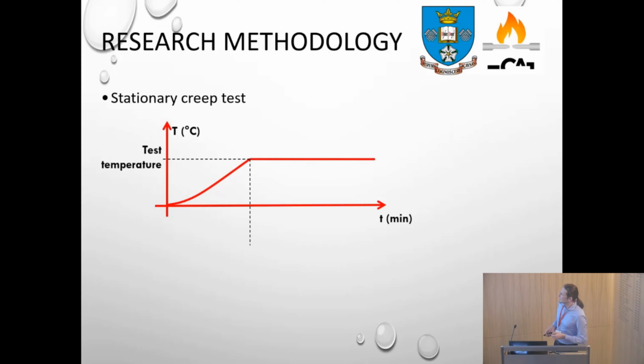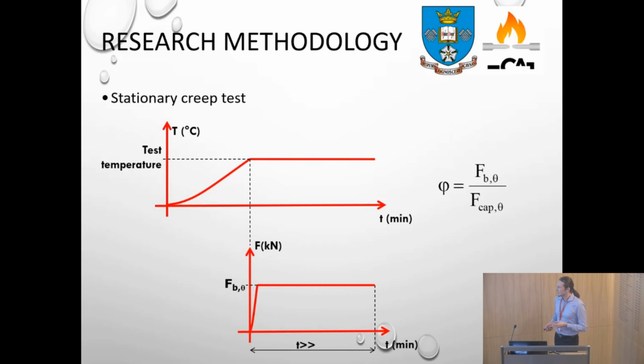Afterwards, we did the stationary creep tests by applying an axial force value, which represents a fraction of the capacity force. That's our phi, which you will see later in the tables. And we measured the displacements of the column and the fire resistance when you apply a certain F_b,θ at a prescribed temperature level.